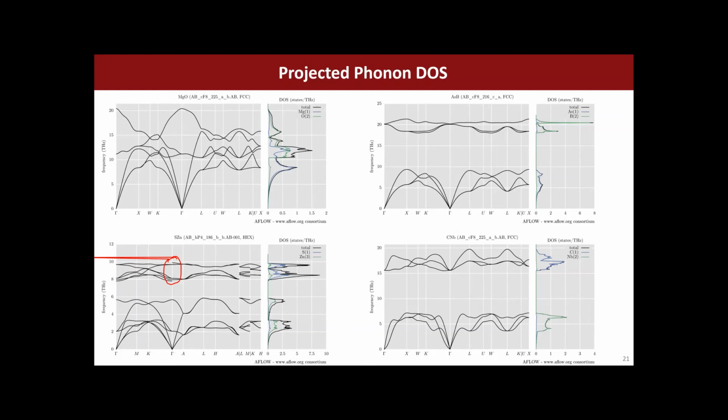And neither do you want to, because actually calculating the Born effective charges is not too expensive. It's actually in the unit cell. So I would rather have a small DFPT calculation with a small cell than an even bigger supercell. Especially because if you're actually going to the wavelength where it is important, the supercell would have to be enormous.